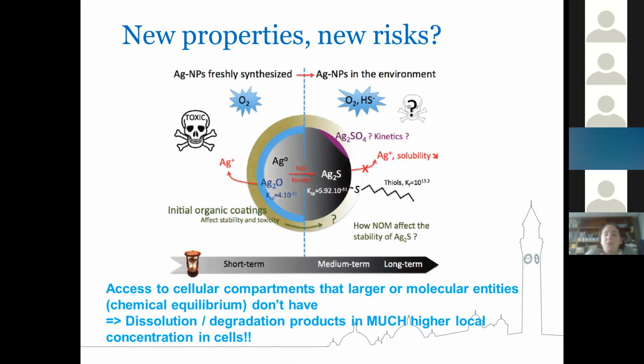The other thing we've got to think about is the new properties that arise as a function of the nanoscale. So I talked about quantum confinement. I talked about the different colors and forms and different crystal structures and things. All of these can potentially lead to new risks. And we need to be looking at those in the short term, the medium term, and the longer term. The nanoscale particles have access to cellular compartments that larger particles or bulk particles, but also molecular entities, don't have. So often molecules will behave quite simply based on chemical equilibrium. So the concentration inside an organism can never exceed the concentration outside, whereas that's not always the case with nanoparticles because they're going in by receptor-mediated processes. So they can actually preferentially accumulate in organisms.